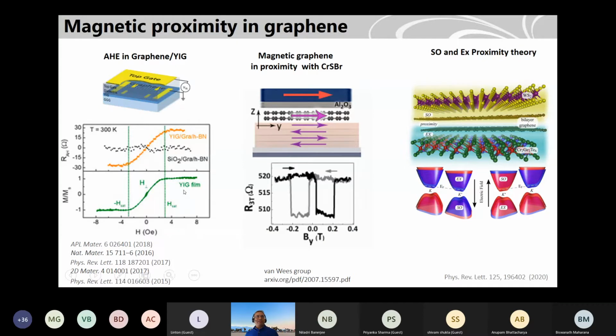And there are some recent developments with graphene with EuS and graphene with these 2D magnets, some showing magnetoresistance. Here you see the anomalous Hall effect. And some theoretical proposals are also interesting, on how you can tune such exchange and spin-orbit interactions with electric field. So in graphene, on one side you can have a spin-orbit interaction with tungsten sulfide, and on the other side you can have a 2D magnet. When you have both exchange and spin-orbit interaction in graphene, you can find some novel phases of matter. So for example, one can also go to the quantum anomalous Hall phase.